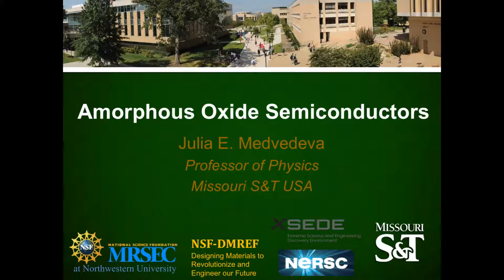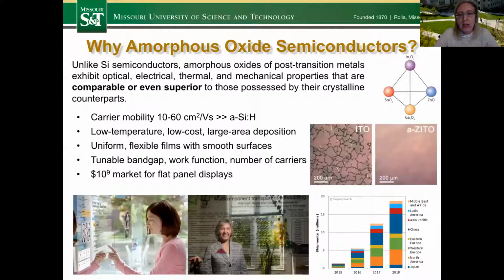So my talk is about amorphous oxide semiconductors. And the first question, of course, is what those materials are. So here are a few fascinating results about these oxide semiconductors. Unlike silicon semiconductors, amorphous oxides of post-transition metals, and here I'm talking about indium, tin, gallium, zinc oxide, exhibit optical, electrical, thermal, mechanical properties that are comparable or even superior to those possessed by crystalline counterparts.